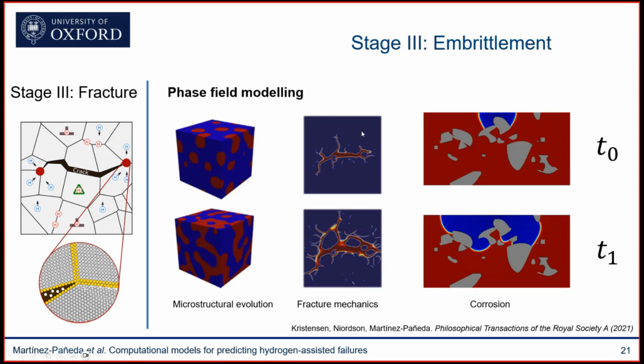But what I'm focusing on today is fracture mechanics, and as you can clearly see, you can capture problems of arbitrary complexity. You can see here multiple cracks, crack branching, coalescence of multiple cracks, initiation of cracks at secondary sites. So no matter what the complexity of the problem is, you can see that the method is quite robust. And one key aspect to emphasize here is that these are not only fancy colors, the predictions provided by these phase field fracture methods are physically very sound.